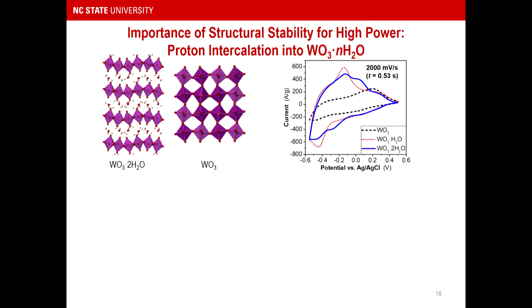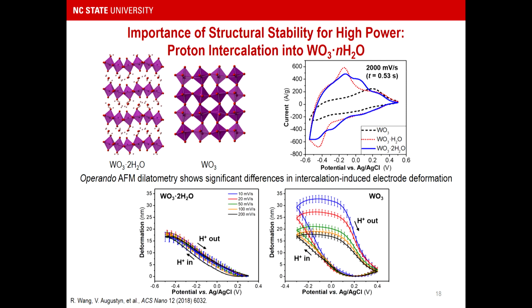And what we see is that when we go to very, very high rates, we're talking about a half a second charge-discharge time scale for hydrated tungsten oxide, we see fairly high electrochemical reversibility for proton intercalation when water is in the structure. The anhydrous material, we still see the Faradaic peaks are present, but their hysteresis is much, much greater. And what's interesting is that initially we thought we would see something like proton moving through these hydrated layers,